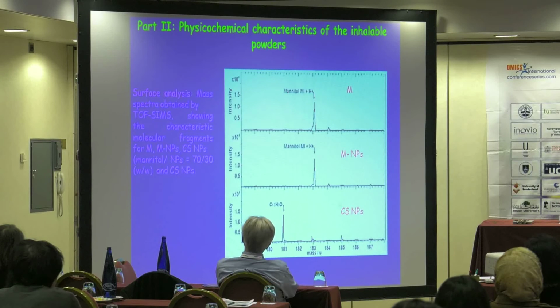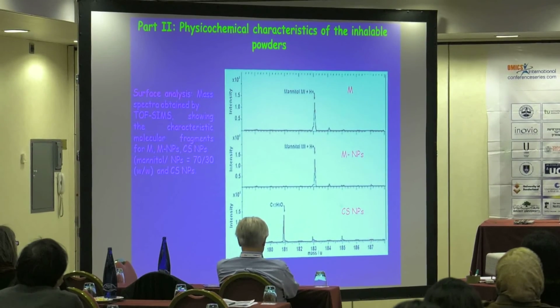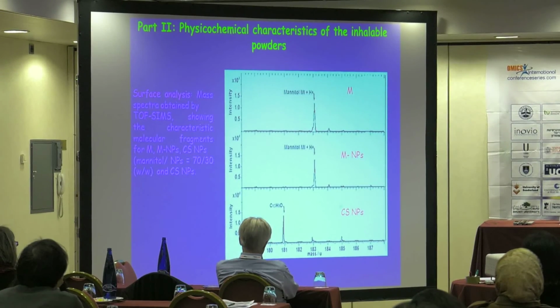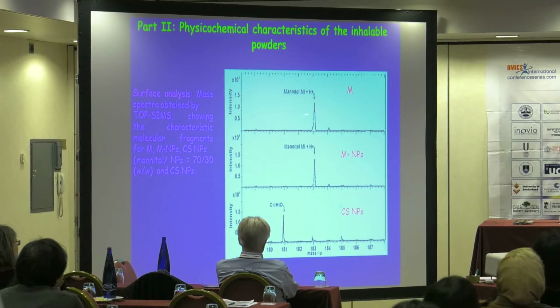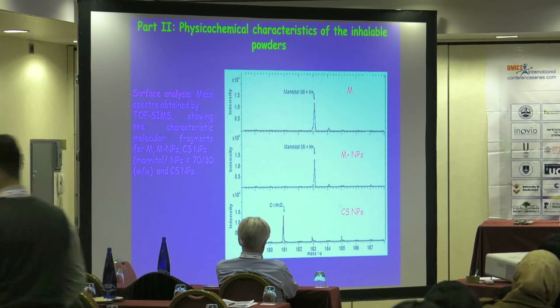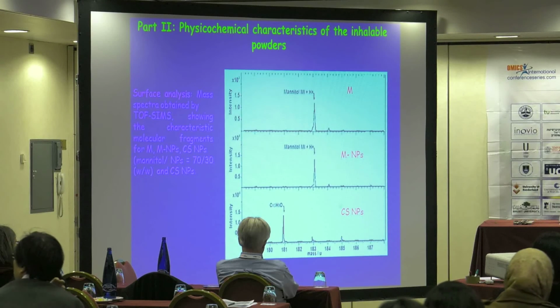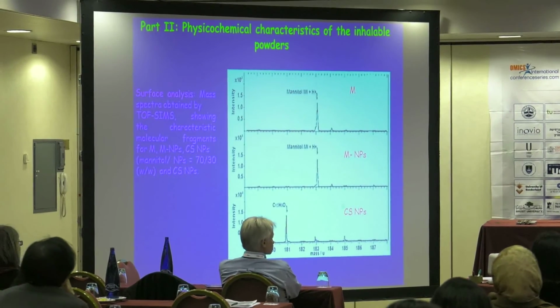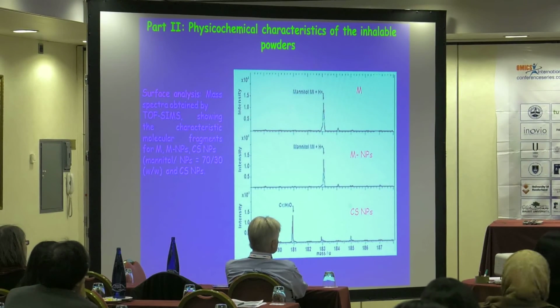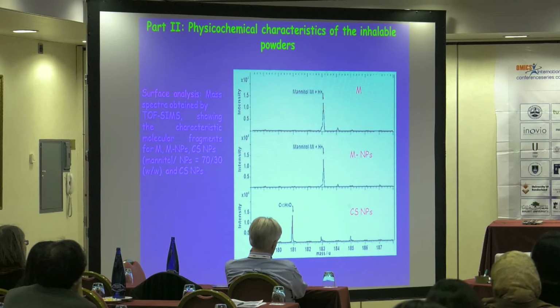Using another technique, TOF-SIMS, time-of-flight secondary ion mass spectroscopy, screening in this region, we could see the spectra of mannitol microspheres and microencapsulated nanoparticles showing the same signals. We could detect a molecular ion of mannitol in both spectra, the blank mannitol microspheres and the microencapsulated chitosan nanoparticles, while this signal was not detected for non-microencapsulated chitosan nanoparticles.